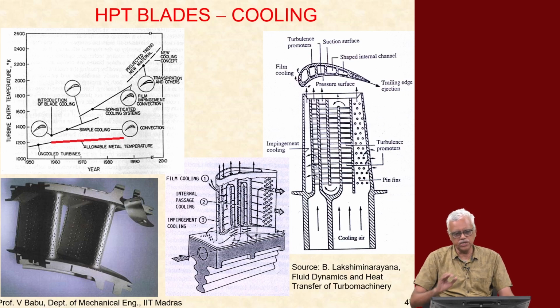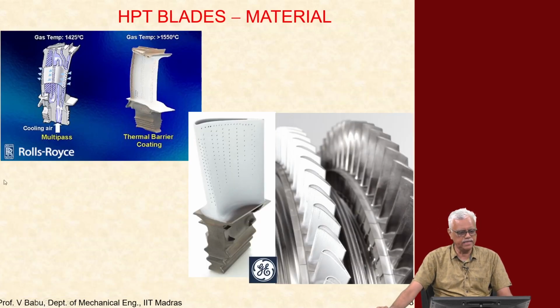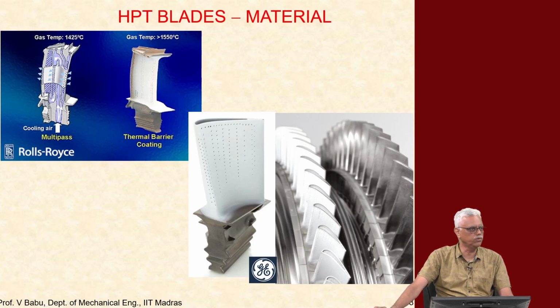So, this is what is done to keep the blades cool. In addition, because the temperature of the blades keeps increasing, what is done today is, you can also see the cooling passages here very nicely, the internal passages. Today what is done is the blades are all coated with the ceramic coating, which is called the thermal barrier coating or TBC. So, the thermal barrier coating allows the operating temperature to be increased even more. So, that is why the aircraft engines, the peak temperatures that they can go to is about 1600 degrees Celsius or even slightly more than that.